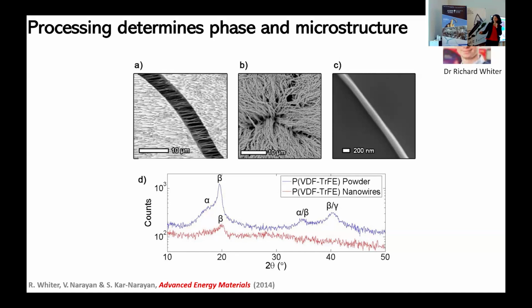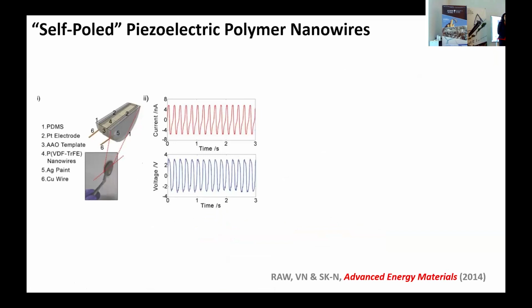the blue line here shows the starting material, so the powder that we started with. And as you would expect, we have different crystallinities, alpha, beta, there are others as well. But when we made nanowires of this using this method, we seem to mostly be able to get our beta phase, which, like I said, is the phase that we're after. So we're already on the right track here.